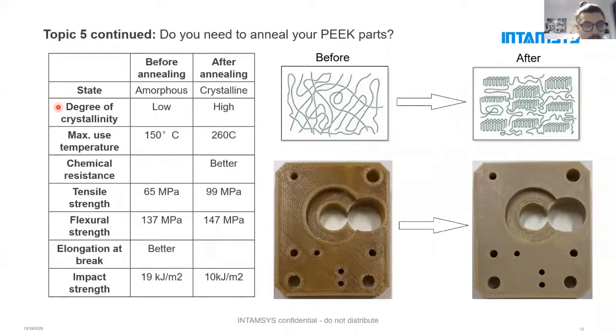On the left, you see a bit more in values what you get out of amorphous parts and out of crystalline parts. So definitely the 150 degrees on amorphous parts is the limit. On crystalline parts, it's 260 degrees. The chemical resistance is better, and also the tensile strength and the flexural strength increase rapidly, especially the tensile strength. If you look on the other hand at elongation, we don't have perfect values to share at the moment, but the elongation is way better. And the same is with the impact strength, where you have 19 kilojoule versus 10 kilojoule, so around 50% less than on amorphous parts.